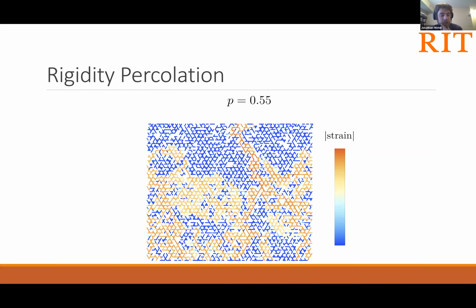So here, we're considering, once again, a low amplitude response. So I'm not seeing strong evidence of strain stiffening in this regime. I guess there's some debate about the role of strain stiffening, just because if this tissue is strained too highly, then that means that other tissues responsible for stabilizing the joint and preventing overly large translations of the joint have failed, and the joint is at risk of catastrophic injury.